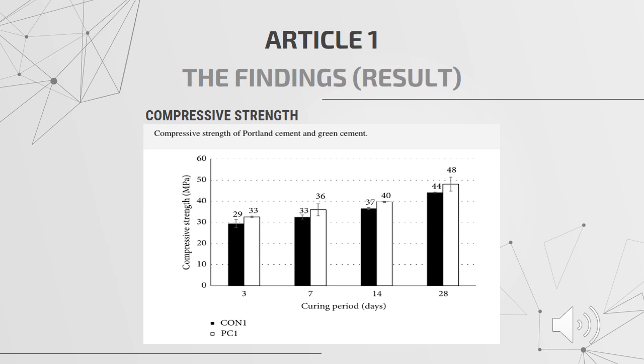This table shows the compressive strength of Portland and green cement. At all curing periods, the strength of the green cement performed better than Portland cement. The results show that the pyroprocessed clay material behaves as a filler at the early curing periods of 3 and 7 days. The behavior of the material after 7 days also shows the pozzolanic effect of the processed clay. The pozzolanic effect takes up lime to form secondary hydrated compounds, including calcium aluminate and calcium silicate hydrates, that enhance the strength properties.